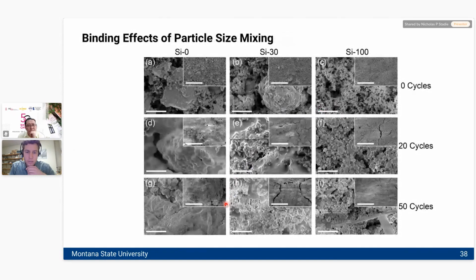Here you have some SEM micrographs of the different electrodes under different lithiation states. Basically, they're all nominally in the same lithiation state, which is delithiated. But we've taken images of our electrodes before lithiation, images after 20 lithiation-delithiation cycles, and then images of the electrodes after 50 cycles. So on the left you have pure micron particles, on the right you have pure nano, and in the middle this Si30 composition.